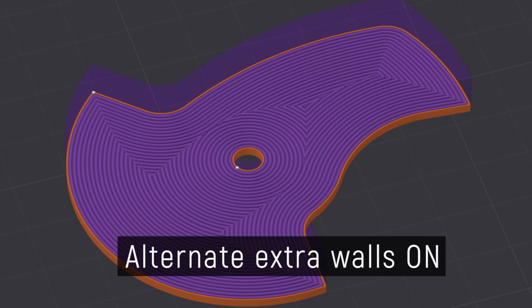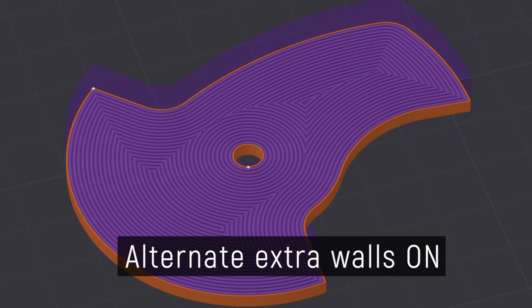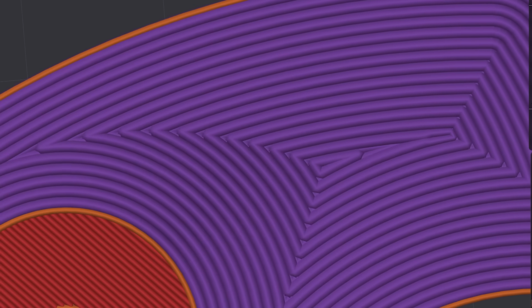You can see that it's forcing the slicer to stagger the pattern now, which allows the molten plastic to flow between the gaps of the internal concentric infill much better, and this in turn makes the part much stronger than if these layers were simply stacked on top of each other. Now obviously you won't achieve the strength of a perfect injection molded plastic part, but we're getting a little bit